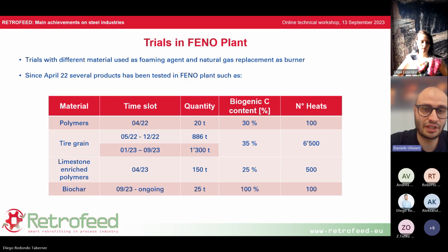And for example, we had around 6,000 heats where we injected this material in order to replace anthracite to create a proper foaming slag. Another experimental approach that we had is to try a sort of blended polymers with limestone that should create a foaming slag inside our furnace. We tried several tons of this material. And of course, we had around 25% of biogenic content.